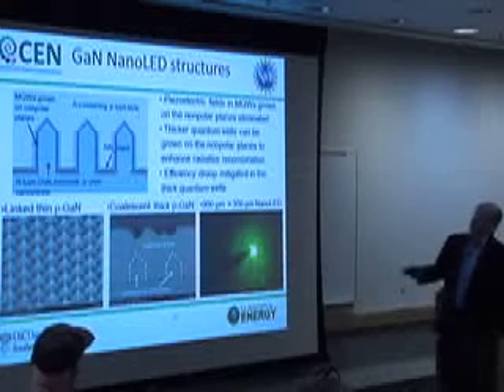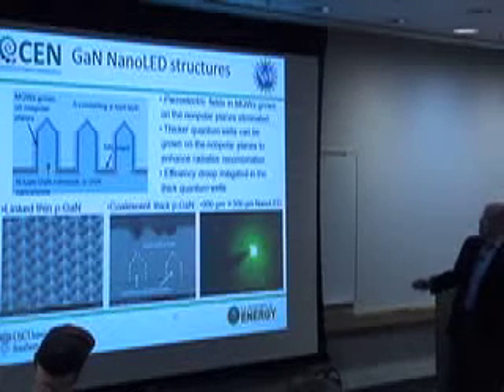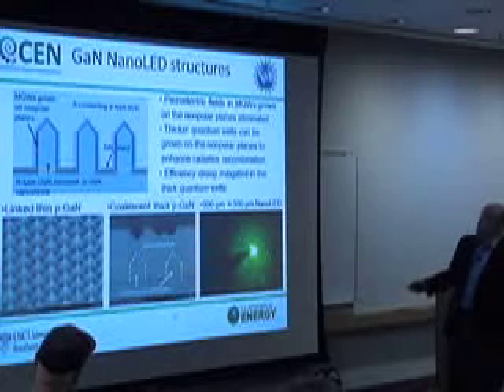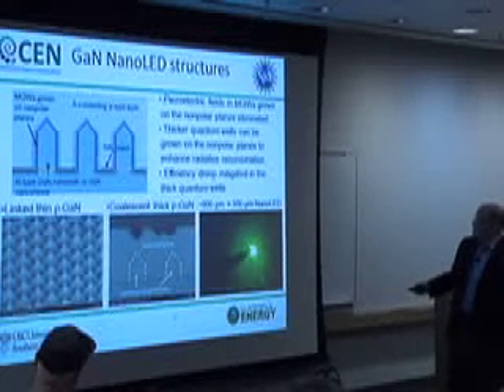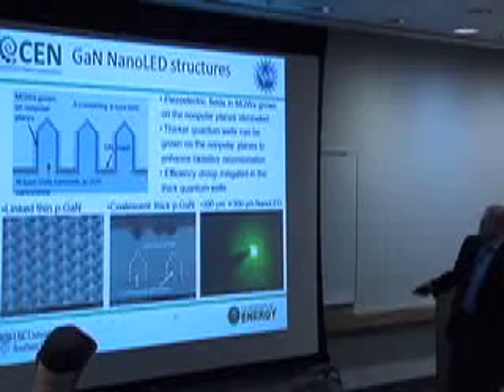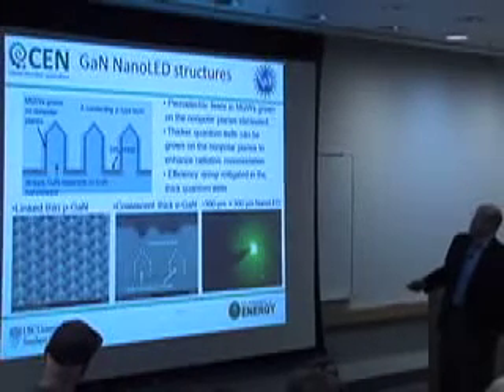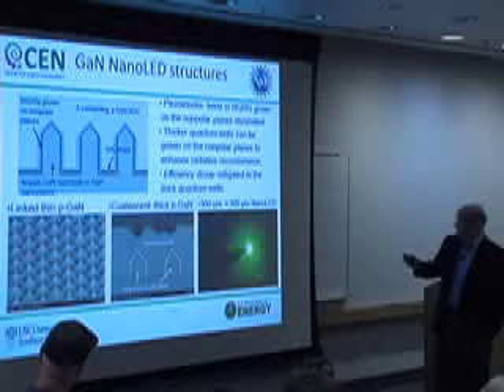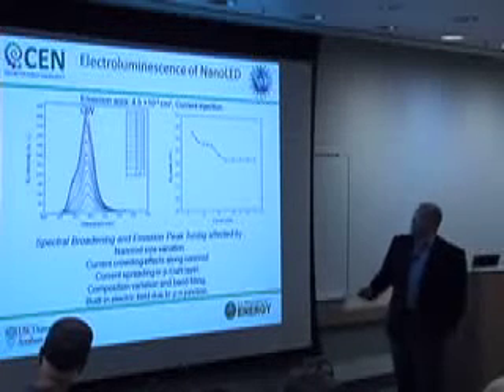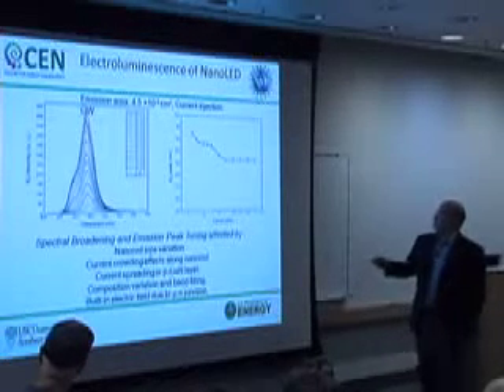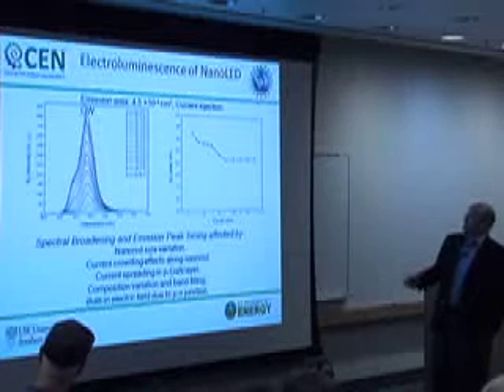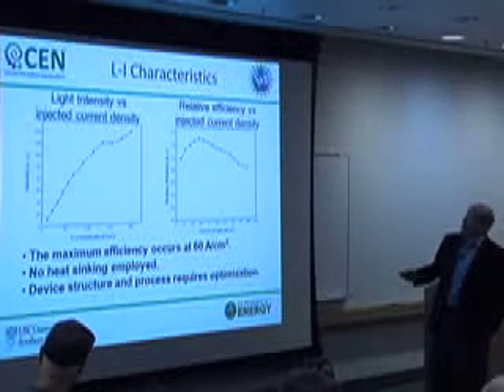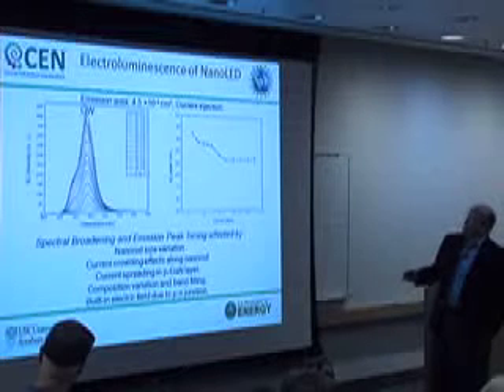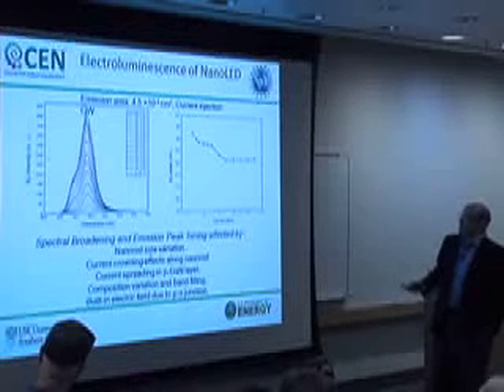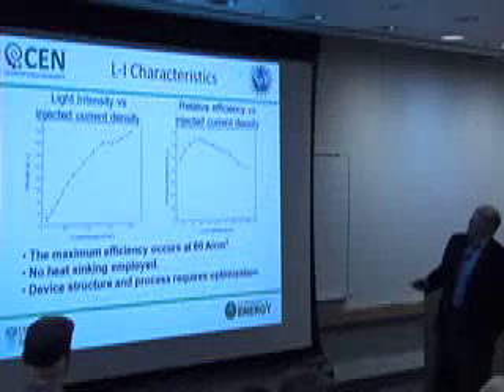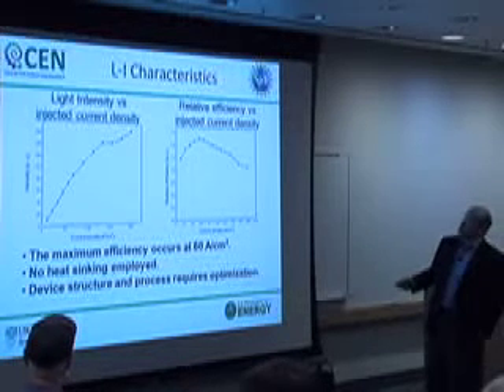We're still fabricating these things with E-beam lithography, so the structures are small, and this just shows the emission from one of them. That's not a true color emission, it's a false color image of the emission. These structures show fairly stable wavelength of emission. There is a slight variation that we think may be related to the non-uniformities that we see in the nanorods. And the light output is a function of injected current.